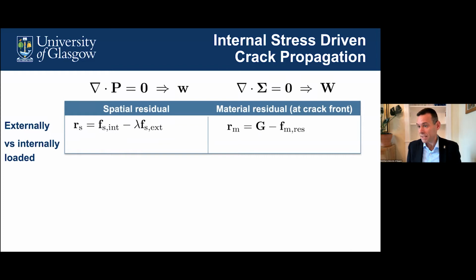Now, that requires an extension to the mathematical framework. So normally when we're doing an analysis where we have external loading, we're trying to simultaneously solve the linear momentum balance equation and the material counterpart. So we end up with two expressions for equilibrium that we're trying to solve simultaneously. And the term lambda here is our so-called load factor, so we can then scale the external load in order to drive the crack propagation.